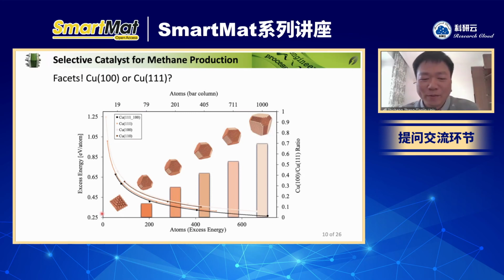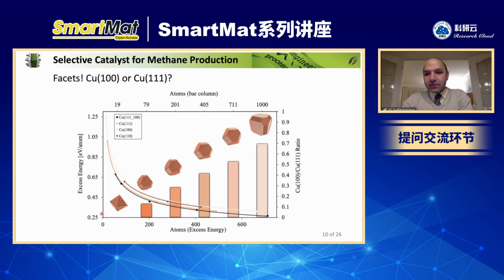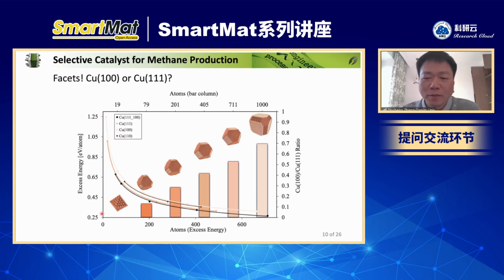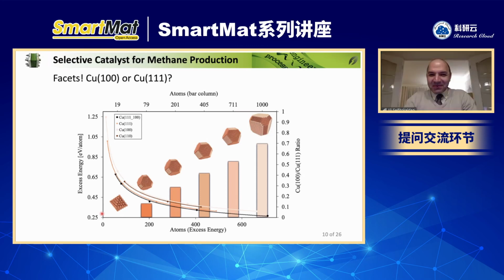Yes. Maybe there is already a published paper for cuprous oxide. They also mentioned this mechanism. They proposed this mechanism on the boundary, which facilitates the CC coupling. Maybe one facet has COH or CHO, another facet has CO, and asymmetrical CC coupling will happen. And we're not sure about copper nanostructures, especially for small nanoparticles and mixed phases. So, very interesting work. Thank you.